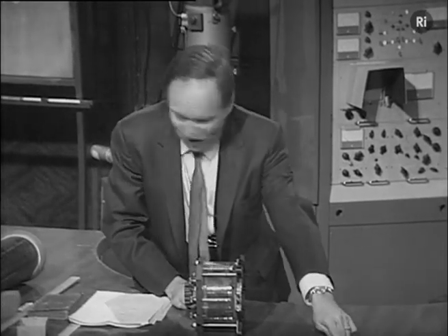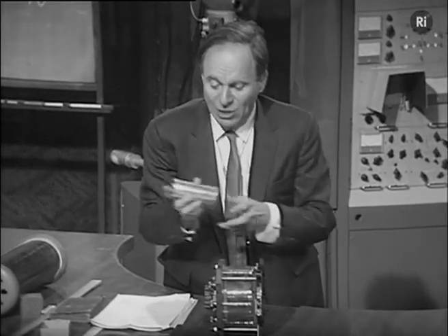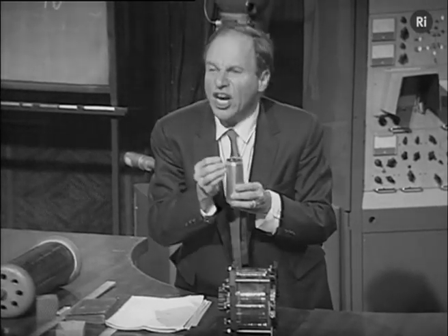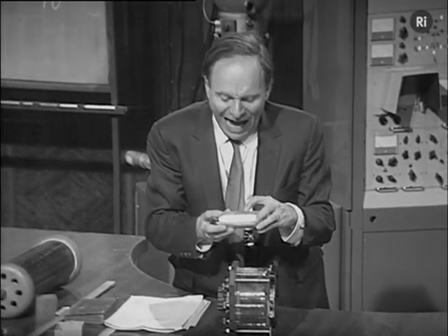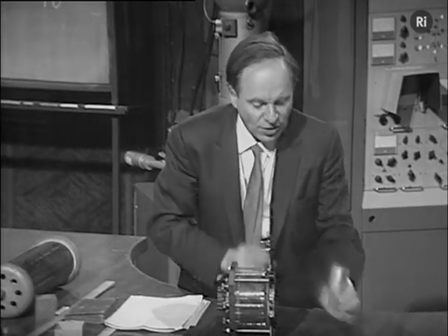that between this and this object, which while it does not look anything like physically, is an electrolytic condenser. Again, it's a capacitor. Again, it has sets of plates, electrical conductors. In this case, very thin aluminum foil wrapped round inside, kept apart not by a thick layer of air as here or here, but by a very thin layer of a tarnish coating on the foil. Such a condenser has a capacity which is 5 × 10⁹ times larger than this one.